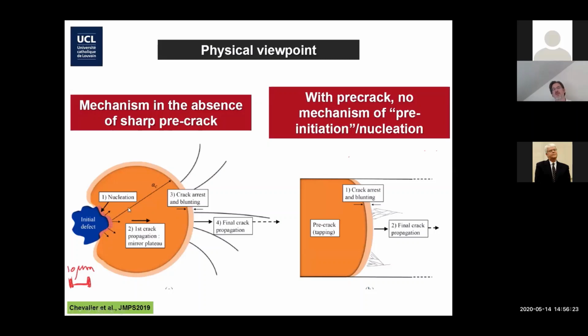For a specimen with a pre-crack, let's say start with a pre-crack here on the right. If you start with a pre-crack, you load the specimen, you get a little bit of blunting, a plastic zone of about a few micrometers in agreement with what you expect, and then the crack propagates.